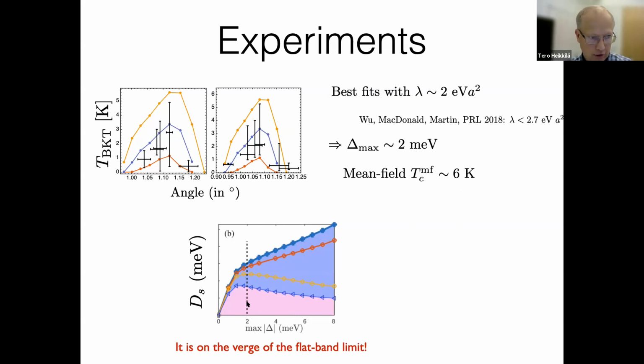And then comparing the different contributions to the superfluid weight. This is a picture of the superfluid weight contributions depending on delta. At small delta, it's mostly this conventional contribution. At larger delta, it's this geometric contribution. We find that already this geometric contribution was very sizable in these experiments.